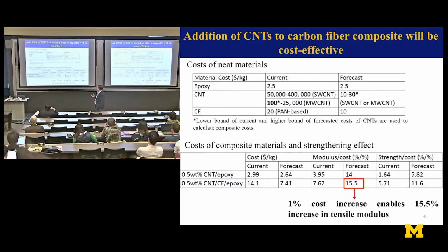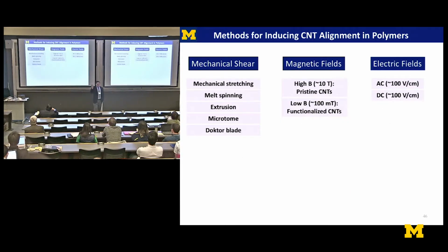And so the key is, could we add that to the matrix of a carbon fiber composite, and by increasing the strength of the matrix, increase the load transfer and reduce the amount of carbon fiber to get the same thing? That turns out, at least on paper, to be economically attractive. And what we wanted to do was actually not only add the nanotubes, but align them in the direction in which the stress was applied.